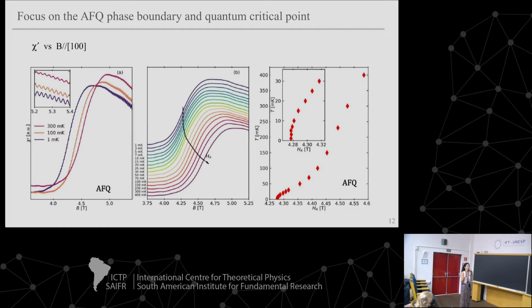But in fact, for what I am talking about now, we didn't want the quantum oscillations, so we took them away. We modeled them, fitted them, and just subtracted them because we wanted to accurately measure the phase boundary, and the modulation from the quantum oscillations on top could interfere with this, so we took them out. And then we differentiated these curves and took the peak of the derivative, so we're actually taking the steepest point of this transition as our transition point.